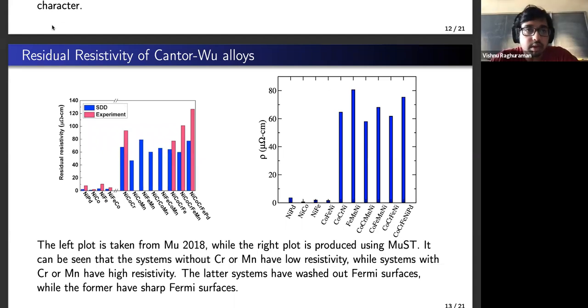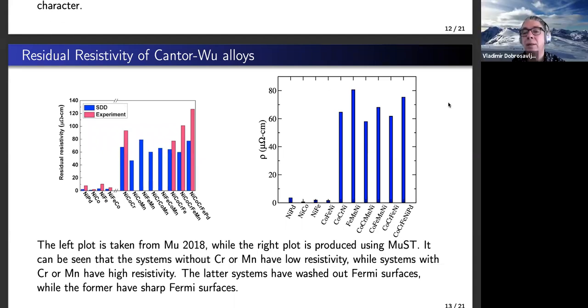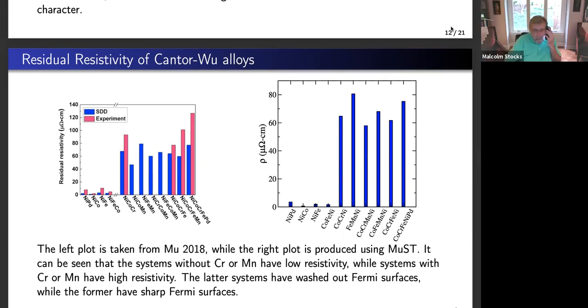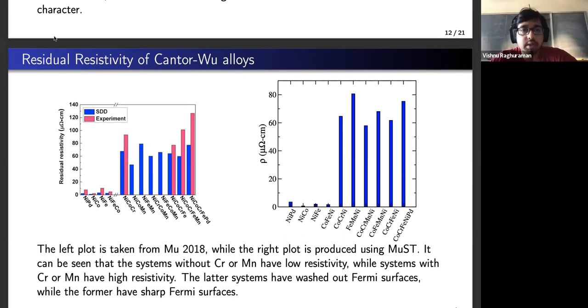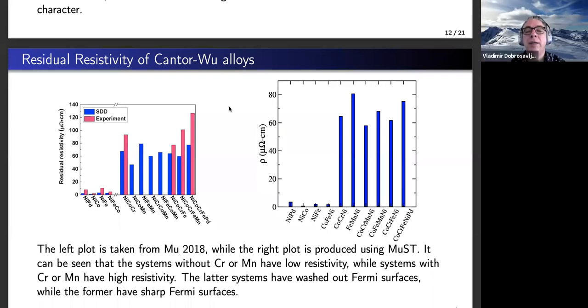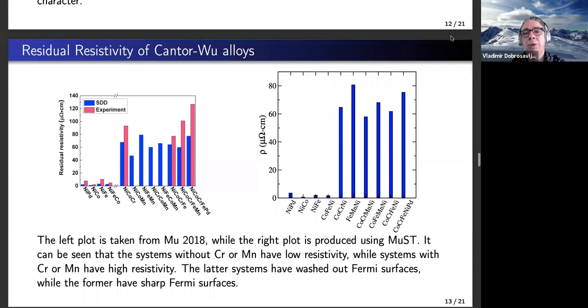And if you didn't put magnetic order, then the results will be very different, right? Yeah, if we don't include spin, then yes, you would expect that. I see. So you're saying that once you put magnetic order, it will create a large random potential when you randomly mix elements, because each element is differently magnetized, right? That's the reason for the strong disorder, right? The magnetic order is creating this strong disorder.